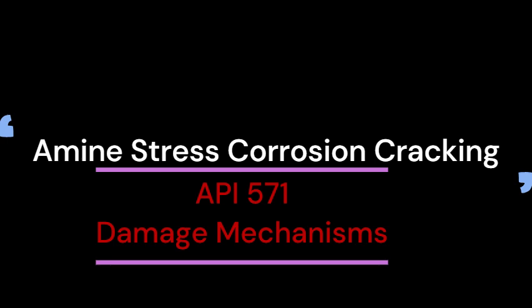So if I'm an inspector and I'm looking at a non-PWHT weld in amine service, where exactly should I be focusing? Is it right in the weld bead itself? Good question. And this is critical for NDT, for non-destructive testing. The cracks start on the inside surface, the process side. They typically run parallel to the weld, but they're usually not in the weld metal itself, or even right in the heat-affected zone, the HAZ.